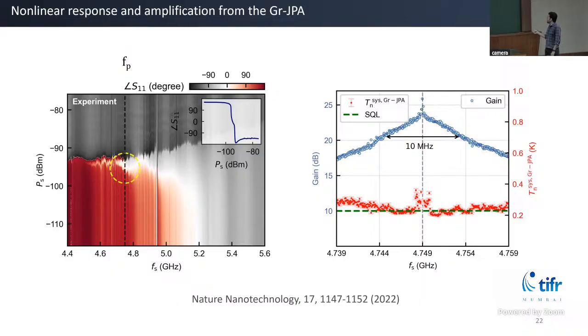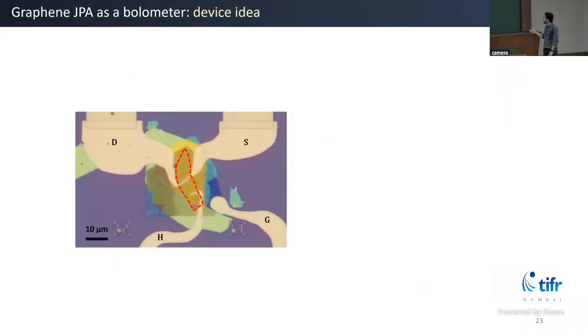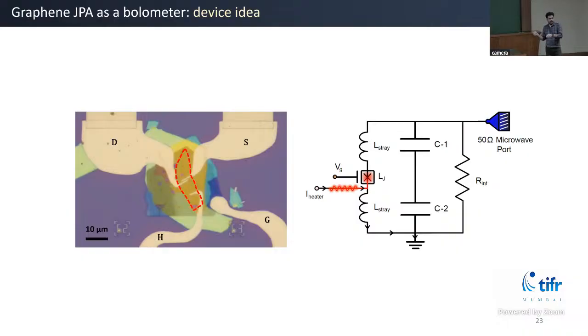Now the next idea is we want to use this device and extend it as a very sensitive bolometer. Our bolometer device looks very similar to the previous device. What we have in addition is again the same resonator, a JJ, a capacitor, a local gate, and now in addition a heater. As I said, in a bolometer you put in heat radiation and that heats your device. Now this electrode in our devices sends some DC current or high frequency current that causes Joule heating. And as a function of that, you see a shift in resonance frequency in the device.